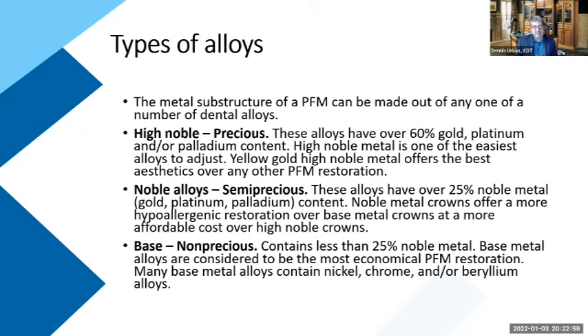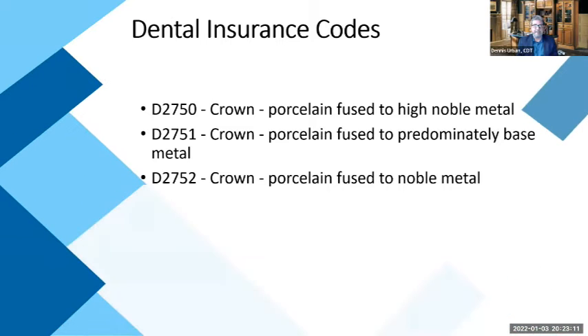And then we have base non-precious metal, which contains less than 25% noble metal, and those base alloys are considered to be the most economical PFM restorations. Most base alloys contain nickel, chrome, or, not so much anymore, beryllium. They've kind of eliminated the beryllium out of these non-precious metals now. And there are your insurance codes. We have dental insurance codes right here for porcelain fused to metal: high noble, base metal, and noble metal.